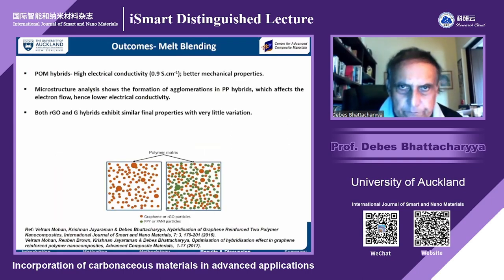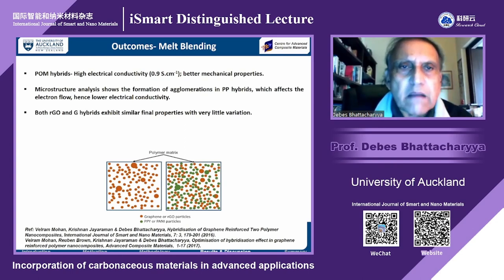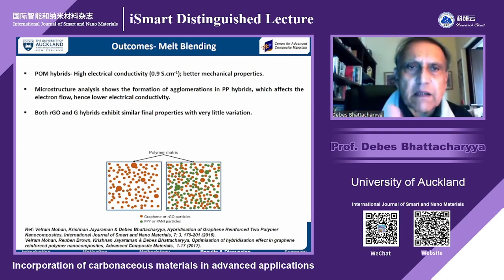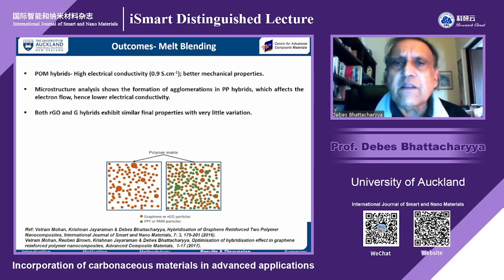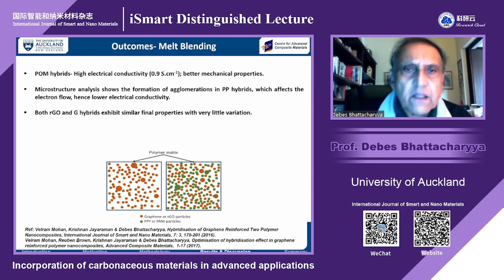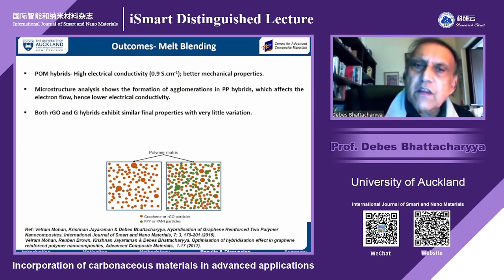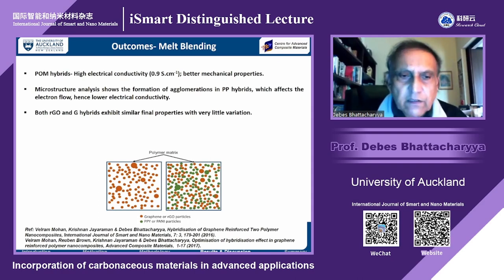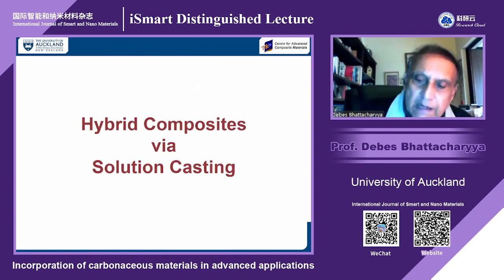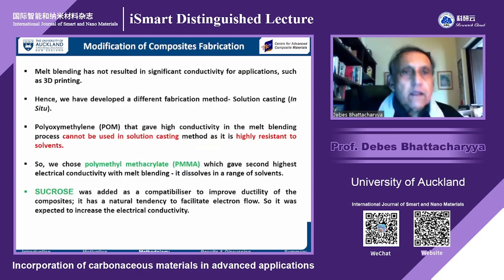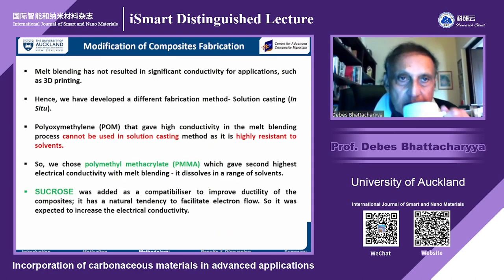But then, if we just summarize the outcomes, melt blending highest, we have shown up to 0.8, but highest we can see go up to 0.9 Siemens per centimeter or something like that. So formation of agglomerations, we can see that both RGO and G hybrids exhibit similar final properties with very little variation. So we had two publications, Advanced Composite Materials and Journal of Smart and Nano. That was the beginning. Then we thought, instead of melt blending, if we go for solution casting, then what sort of result we might get?